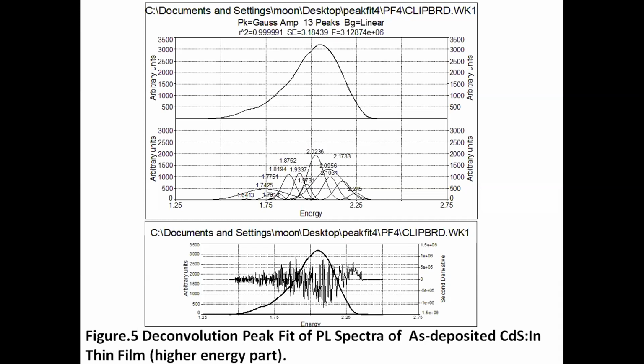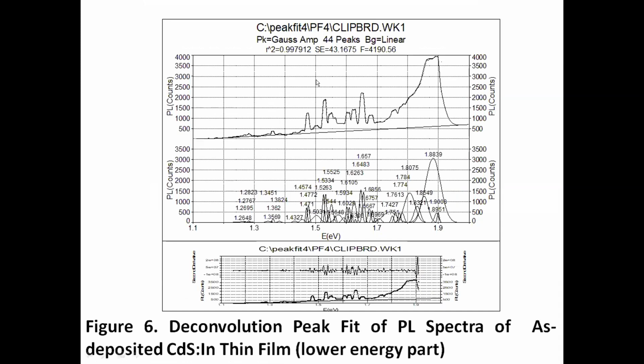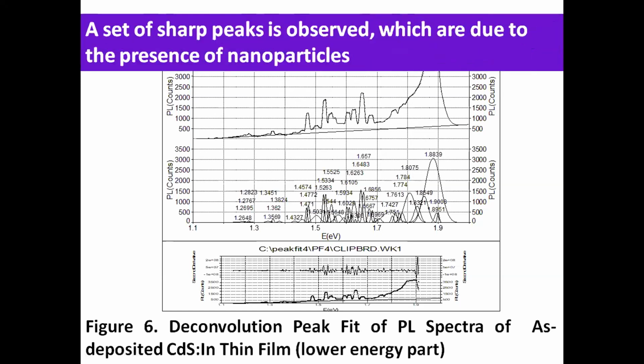Now another peak fit was made for the part in the red and infrared region, and as you see here, the sharp peaks are related to the presence of nanoparticles. Here you have the infrared region and the tail of the red region. When this is fitted to Gaussian peaks, it gave 44 peaks. Also the second derivative was used to confirm the positions of the peaks, where the positions are recorded on the figure.